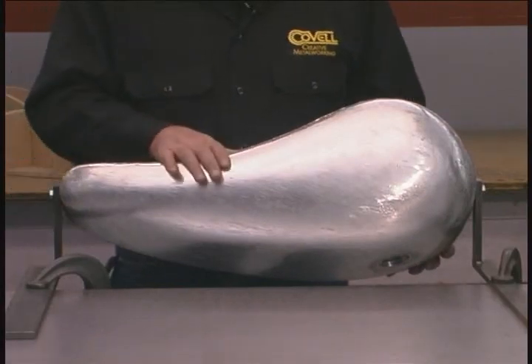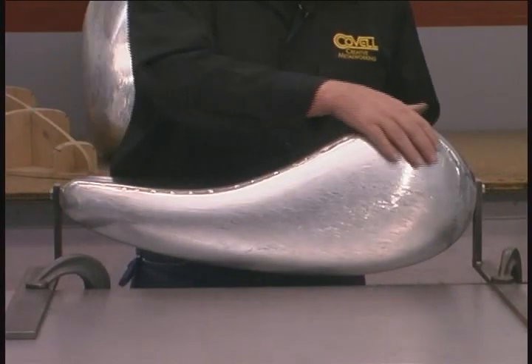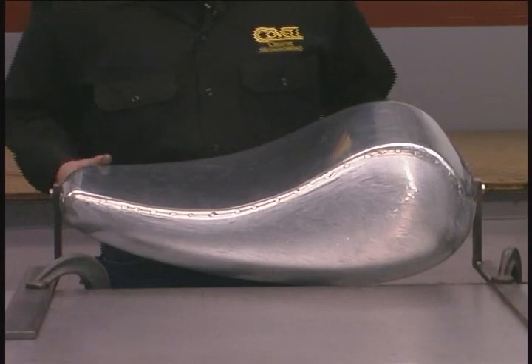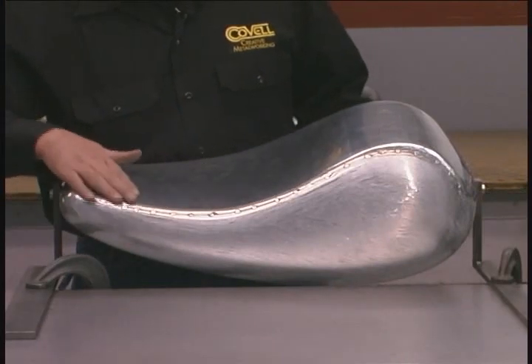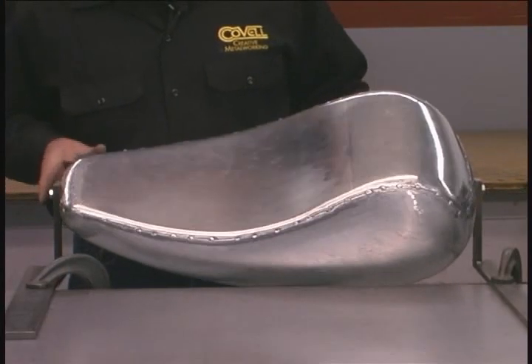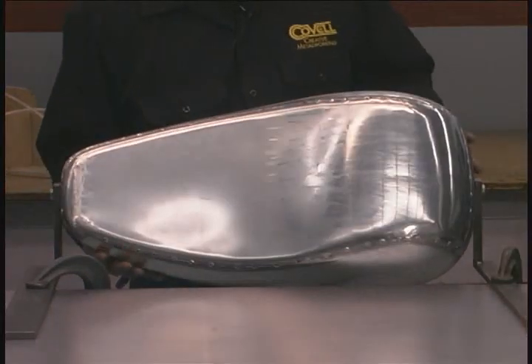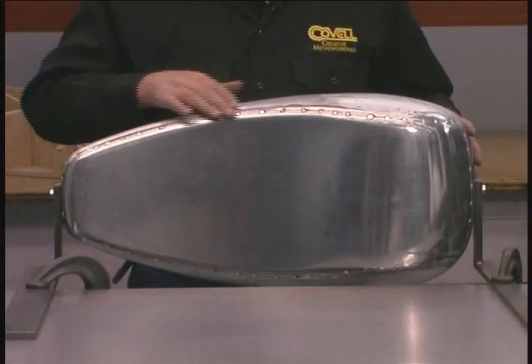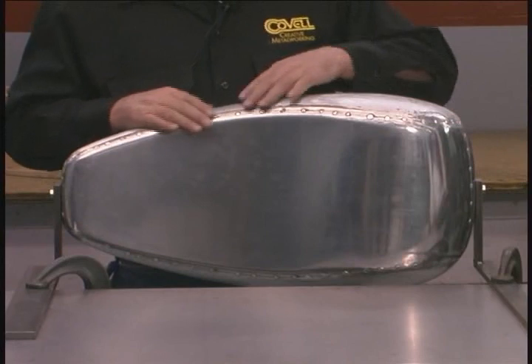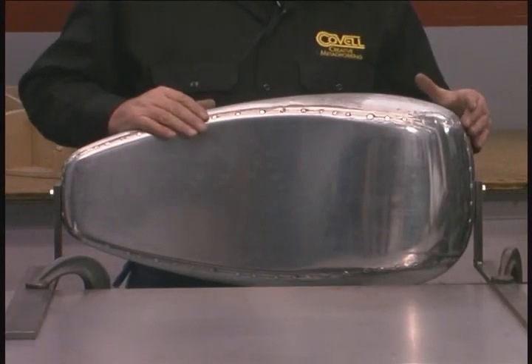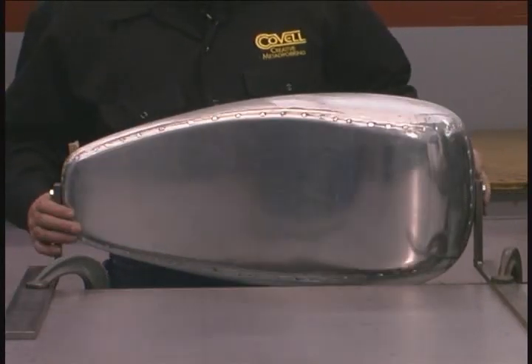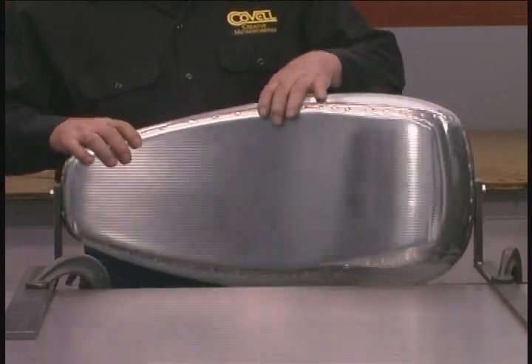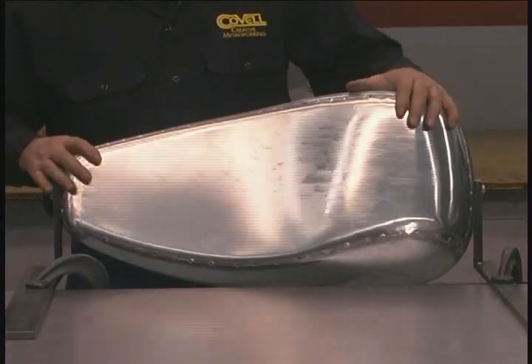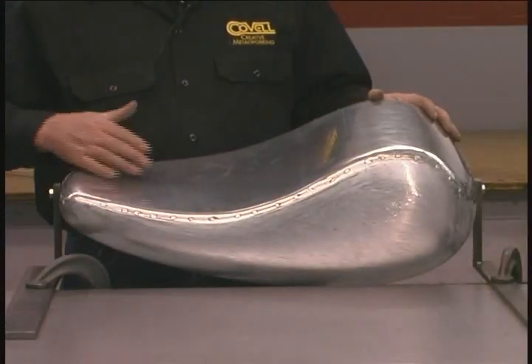So before it's welded, you have to be sure your fit up is just as good as you can get it. And because there's so much contour on the edges to be welded, they're not going to distort very much with the welding process. So I'm going to TIG weld this bottom seam. I want to demonstrate that both oxyacetylene and TIG welding are good processes to use. And after the weld is in place, we'll sand the weld down and we'll be ready to fit the tunnel into the tank.